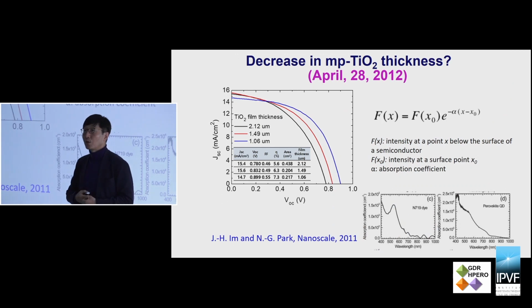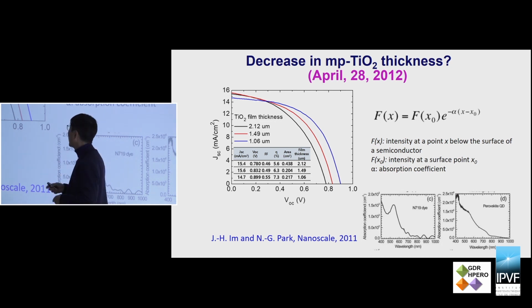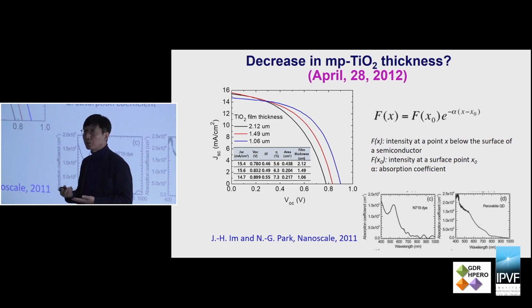But because we know the perovskite material has an order of magnitude higher absorption coefficient than the conventional N719 dye, that means if you increase the absorption coefficient, then you don't have to increase the titanium oxide film thickness, because penetration depth is inversely proportional to absorption coefficient. So a thinner film will be okay, it's better.